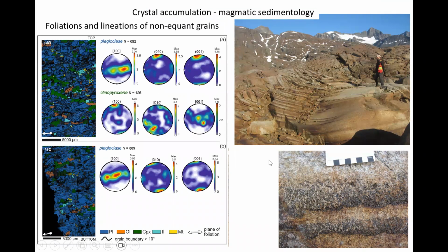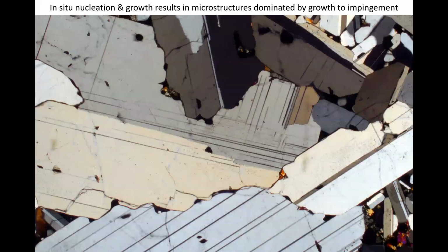Just a sedimentary example. So this is just a quick example from the Skaergaard again. We've got these elongate plagioclases in these layers, which are formed by magmatic density currents coming down, and the plagioclases form these beautiful lineations. But if we've got in situ nucleation and growth, you've basically got the nuclei there, everything's static, and the grains are just growing until they impinge. And that gives a very characteristic microstructural signature in that the grain boundaries bear no relationship to growth faces because they just grow until they impinge, and they're randomly oriented usually.